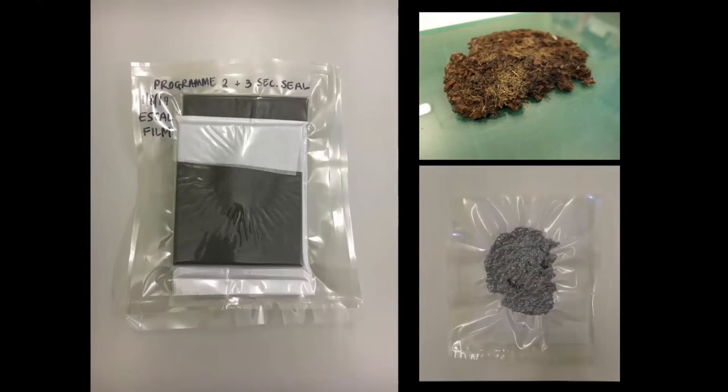30-gram Bondina, a non-woven polyester material with an extremely smooth surface, was selected as a support, and 7mm black Plastazote, a cross-linked closed-cell polythene nitrogen expanded foam, was selected as a secondary support and cushion for the Bondina-wrapped manuscript. These layers served to disperse the vacuum pressure during enclosure. Finally, we used an anti-static gun to dissipate any static that might exist from all of these materials.